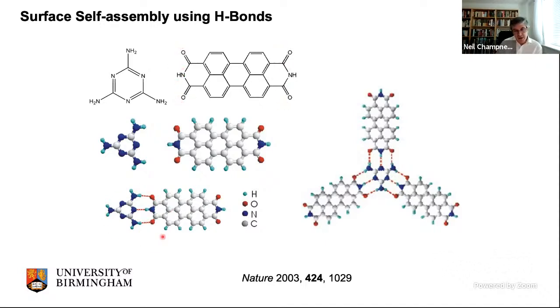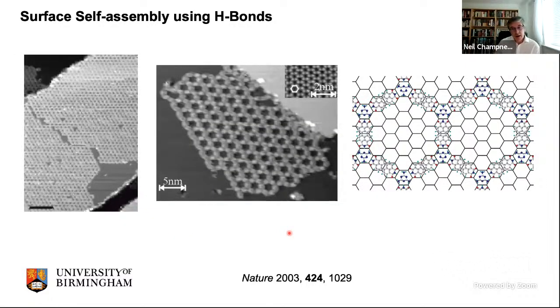So you should form this triple hydrogen bond. Each melamine should have 3 of the imides sitting around it. Then the melamine should sit at the other end, and you should make a honeycomb structure. So this is what you see. These are the STM images. We can grow them over whole surfaces. Over here, you can see each of these white features is the perylene diimides, that long diimide molecule. And you can see 3 of them coming together at a vertex, which is where the melamine sits.